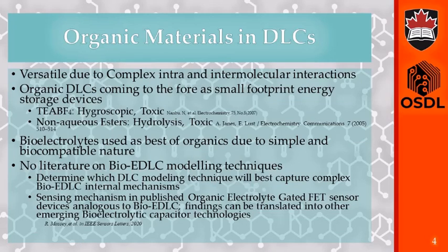Organic materials benefit from being lower cost and with higher mechanical flexibility than conventional materials. In addition, complex intra- and intermolecular interactions introduce great versatility, which is the reason why organic DLCs are gaining traction as the next small footprint energy storage device. However, common organic electrolytes such as tetraethylammonium tetrafluoroborate or non-aqueous esters still require highly specialized fabrication environments. Bioelectrolytes are a further improvement on organic materials as they can be processed without a specialized environment, which reduces processing costs, and you end up with a biocompatible final product.